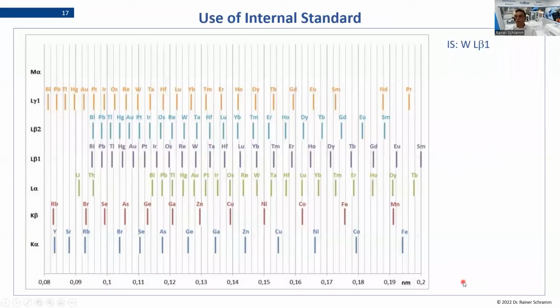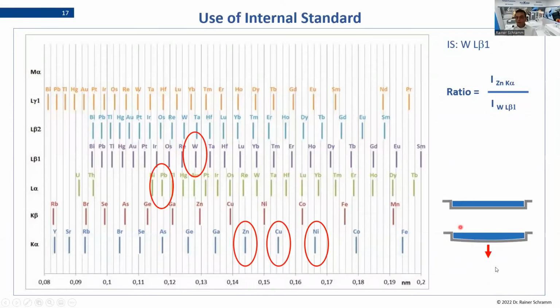And now let's also have a word to the internal standard. Why are we using this? Mostly the idea is to use the platinumware as long as possible. And when you look on these lines we use for determining the main components in that application, so we have the lead L-alpha line, or we have the zinc K-alpha, copper and nickel K-alpha, and tungsten is just in between, so it's a neighbor element. And if we now would form the ratio between the analytical line and the internal standard line, then we see that all effects like bit consuming of the platinumware, the dish, both intensity will be affected in the same way. That means the ratio here is just the same.